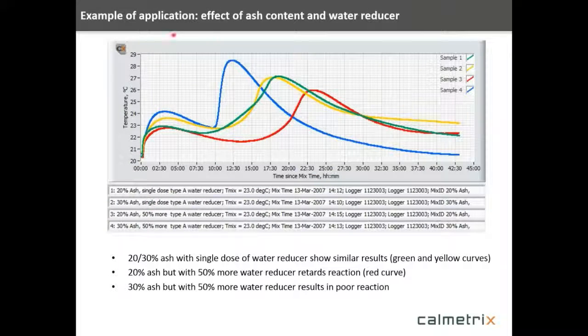Let's talk about another example. Here's the effect of ash content and water reducer. So here we're looking at 2 different constituents within the concrete, and we're looking at various combinations of those. This was done here on a semi-adiabatic device. We know that because we're plotting temperature here as a function of time. And the implication here is that the 2 curves, the green and the yellow curves, which illustrate the data at a 20 and a 30% ash content with a single dose of water reducer, those curves look fairly normal and pretty consistent with one another.